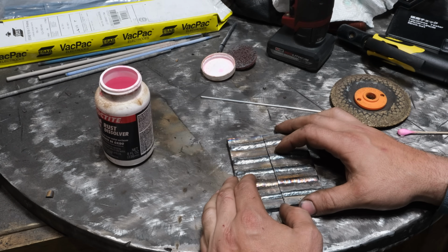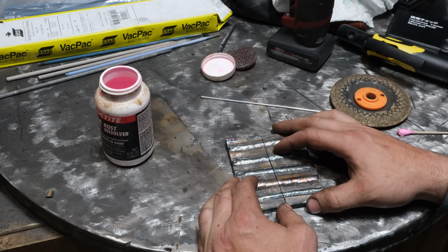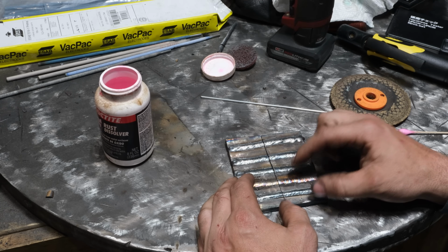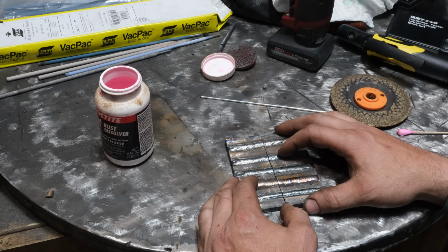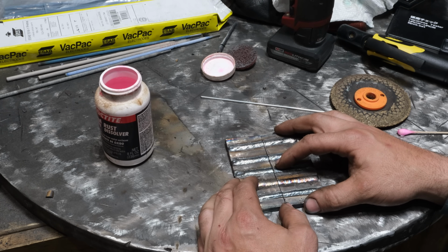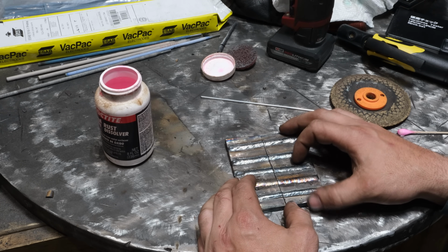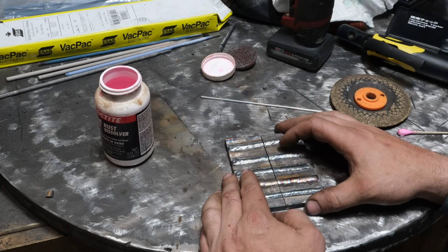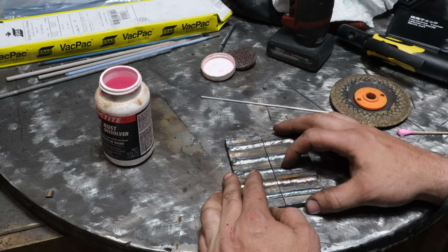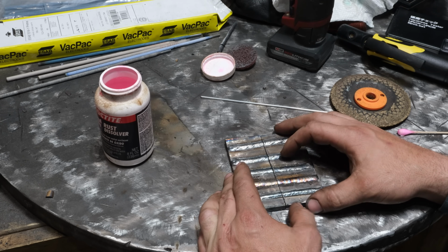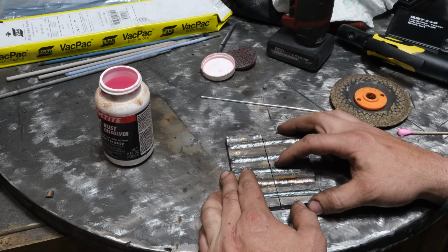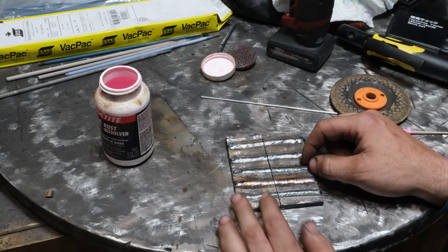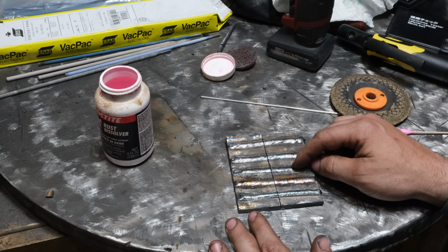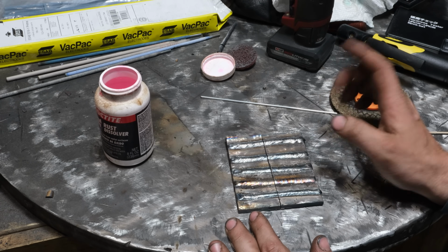So that was pretty interesting. And I gotta say, I'm kind of surprised the 11018 didn't crack. I'm not surprised at all that the hard face did. Ran a little bit hot and had a little bit too much dilution of that material into that plate. And that is to be expected. And that's one of the reasons why you don't use hard face to actually weld something together, which is gonna be pretty interesting when we actually bend test something that I welded with hard face. So speaking of that, let's go and bend test.